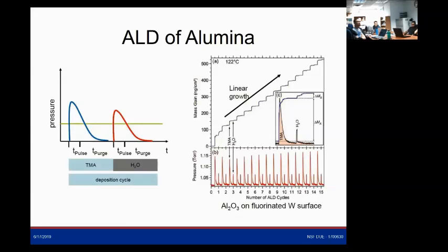Okay, so we will send pulses, of course, the first pulse and the second pulse of the precursor. The first one will be the TMA, the second one will be the water. So once you look at the histogram, it's going to look like this, okay? That's why I was saying it's not going to look like a very sharp pulse, but because of the methane release, it's going to have a long tail, because the methane will be released, and then that's going to add some increment to the overall gas detection.